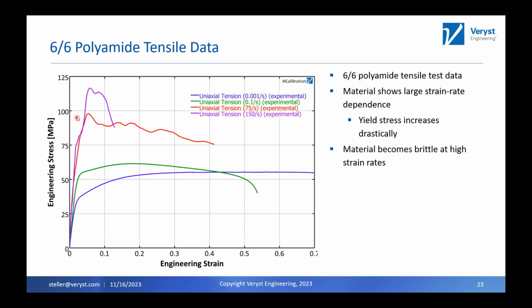So you can see there are 2 big things that change. You can see the behavior here below 10% strain. We've got a much higher yield stress as we go to those higher rates, and this material became more brittle at the higher rates as well. And so if you weren't aware, that is something that you want to think about when you're designing your test plans. If you're doing things at impact rates, you want to make sure you get some data up there. If you're doing things very slow, you want to be in that right ballpark as well.